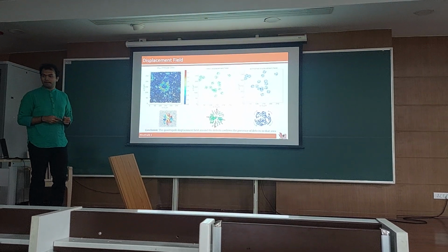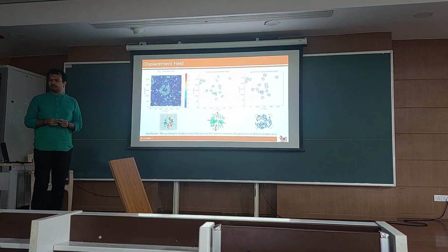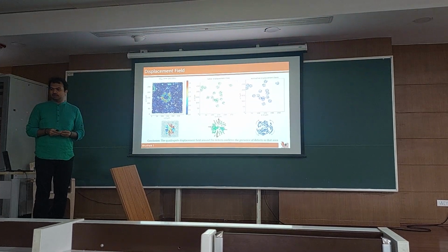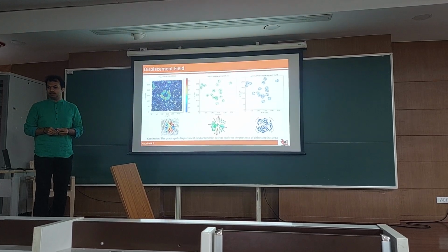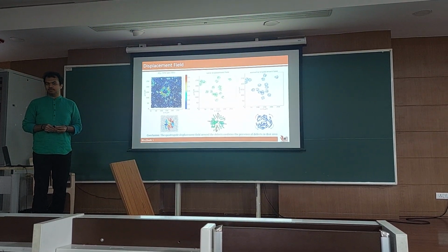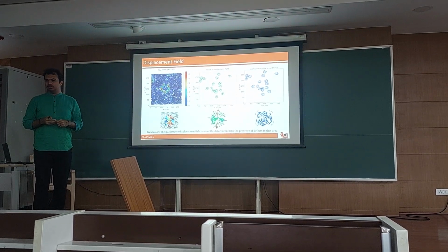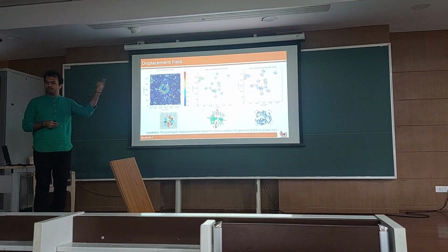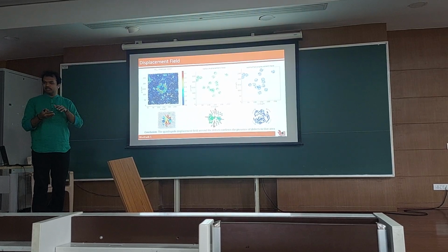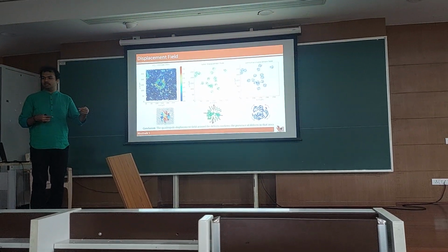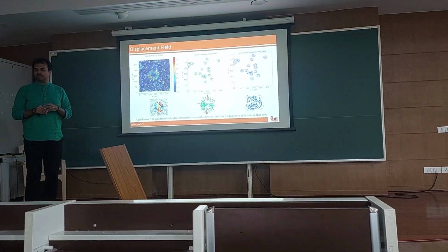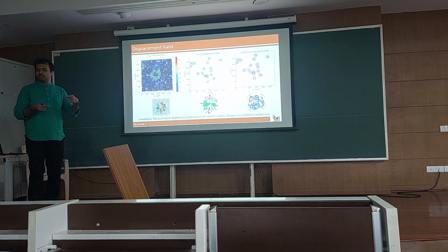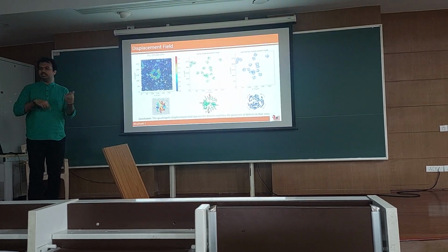Is that the definition of a defect? Yeah, it is a post-factum analysis of what happens under plastic deformation. Suppose I look at a solid, I cannot say where the defect is. But when shear plastic deformation is applied, wherever something different is happening, that is where the defect was, or the defect is formed. The defect should have been present in that region, because more rearrangement is happening there. It is like a reverse analogy. In a crystal, wherever a defect is there, we see more rearrangement happening. But in an amorphous solid, where rearrangement is happening more, we call it a defect.